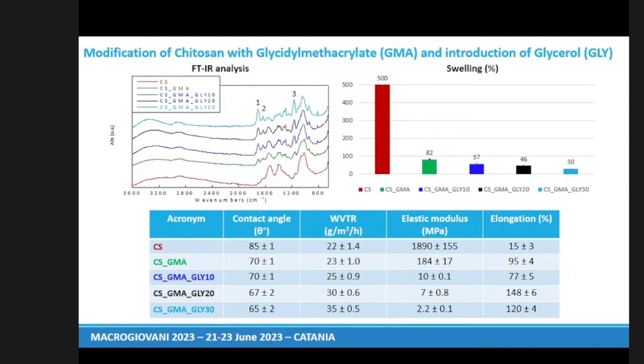In the first case, we can see the formation of new peaks. In the first case, we have the stretching of the ester carbonylic group. In the second case, the stretching of CH relative to the double bond. These two are due to the GMA introduction. In the case of GLY, we can see the formation of a third peak that is related to the CO stretching of the tertiary alcohol.